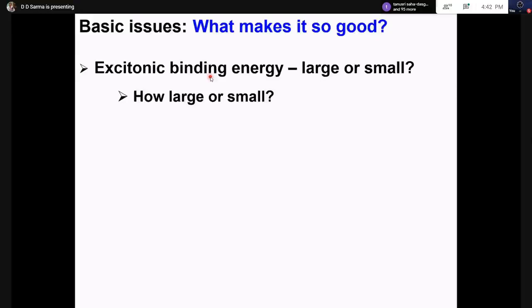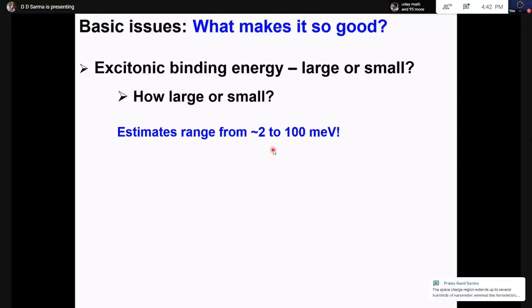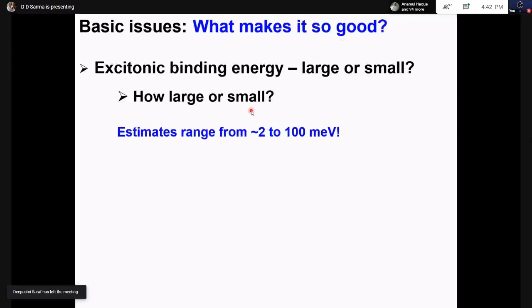photovoltaic material. But the estimates range from 2 to 100 millielectron volt. Now, the question is whether the excitonic binding energy is large or small. Whenever I ask that question, that means I have in my mind a comparative point, larger than what, smaller than what. That scale is the thermal scale, the room temperature thermal scale, which you know is about 30 millielectron volts. Even if it is twice that much, let's say 60 or 70 millielectron volt, the thermal energy will be enough to split it apart quite frequently so that they can diffuse again. But if it is going to be 100 millielectron volt, then it's too high and it will not separate.